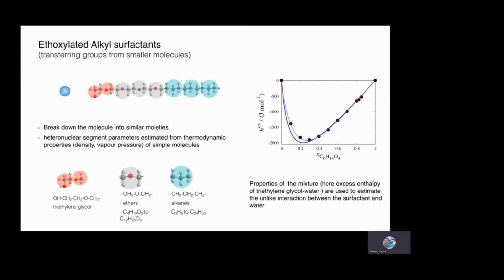So at the right-hand side, you see the fit that we used to fine-tune the triethylene glycol mixture by using the excess enthalpy as a function of the mole fraction. And these thermodynamic parameters were then transferred into the general model.